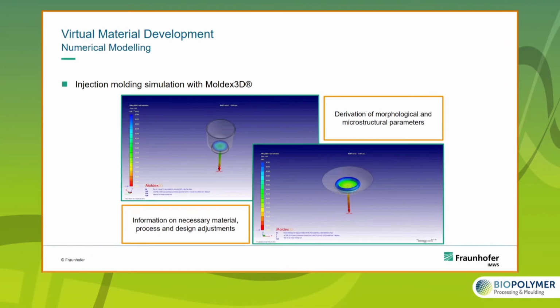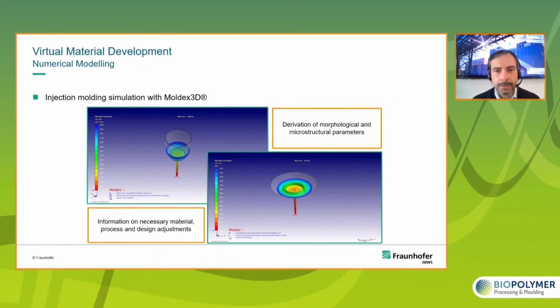In the injection molding simulation, we work with the software Moldex3D. And the same here, we can vary the material properties like viscosity or flow behavior. We can also vary the processing parameters. And by doing so, we can find the optimum process setup and also find out how the material behaves under the processing. And for us, this is very important because this is the final step in our optimization cycle, which can have influence on the microstructure of our materials. So variation of morphological and microstructural parameters can happen. And this is very interesting for us to find out by those simulations. And in doing so, we find information on necessary material, process, and design adjustments.